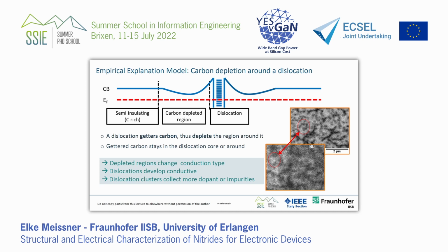the material and for the HEMT structure, because it means that if you have, like I said, an evenly distributed carbon content in the gallium nitride buffer that you want, you have a region with a dislocation or many dislocations where you have gathered the carbon, which comes from the neighborhood. So in the neighborhood it's not there. The material itself should be insulating with the carbon, but what you do, if you deplete the region of carbon, you make it more conductive. So the insulation is here, not all over the area, and you create something like an N-type region around a dislocation. So what you create is an envelope.